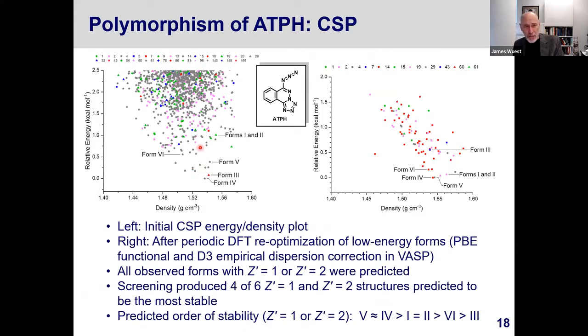So on the left here is the initial force field level crystal structure prediction plot. And you can see, there are a large number of different possible structures here, all within a very small window of energy. And that certainly raises the question of whether or not at this particular level, the predictions can be considered to be accurate. And so Graham and his group carried out a re-optimization using density functional theory to explore what would happen to the number and order of possibilities in this narrow 0.5 kilocal per mole window.